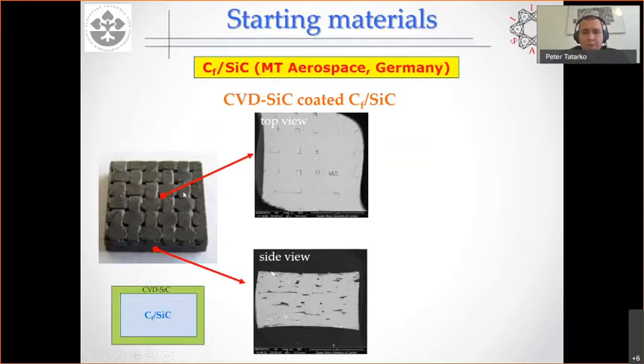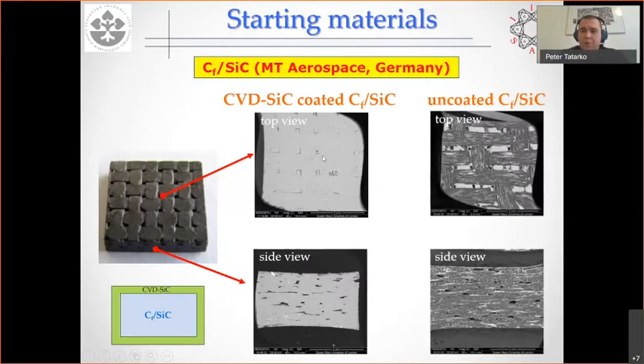One important feature I would like to point out here is that these materials are always covered by a CVD silicon carbide layer. Here you can see the top view, this is the backscatter image, and you can see the side. You can see a very uniform light gray phase, which is the CVD silicon carbide. Just to see the difference, here you can see the uncoated material, and this light gray phase is the silicon carbide from the matrix, but you cannot see such a uniform layer of CVD silicon carbide. The reason they use this layer is to have better oxidation protection.